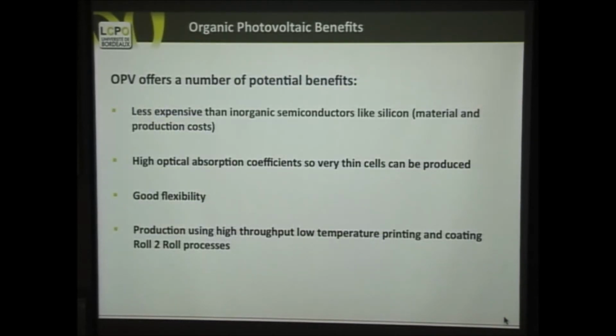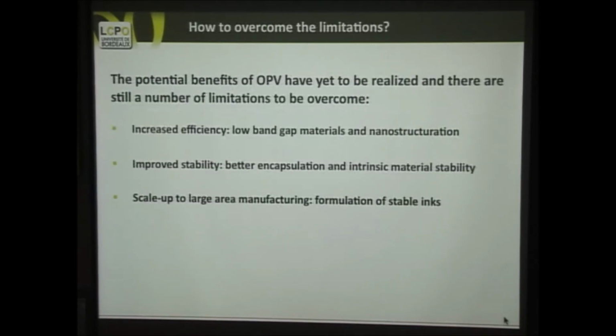Why we have room and why this can be important, okay? Well, first of all, we have very inexpensive semiconducting materials, the polymers or the small organic molecules that have semiconducting properties. One very important point that I understood when I was an undergraduate in Greece is that these molecules, like the carotenes, where you have alternating single and double bonds, have an enormous strength of light absorption, which means that you can have a thin film that absorbs more energy than a thick film of silicon, you see? So that's an advantage we often forget. You have good flexibility, and eventually we can produce it with roll-to-roll.